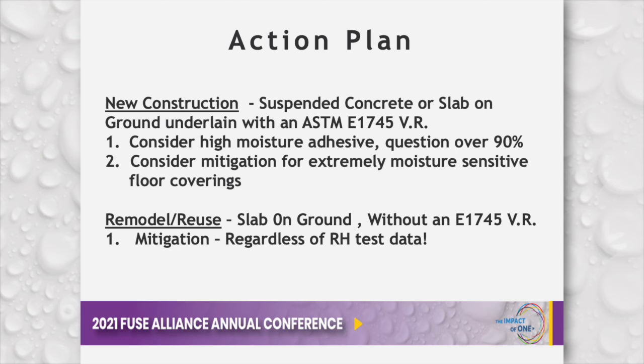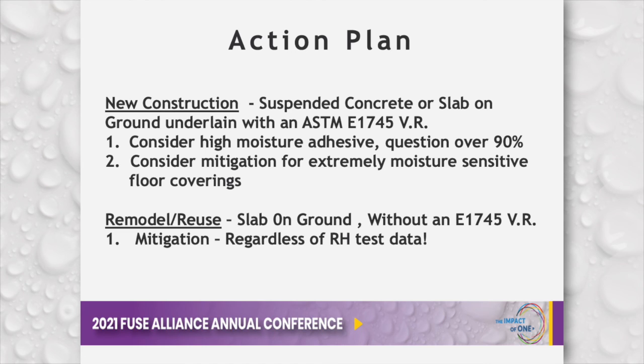So I would always consider mitigation for extremely moisture sensitive floor coverings. And frankly, unless I know how that building is going to be HVAC controlled, I would consider it for anything over 90%. But I understand if you have to use a high moisture adhesive without that ability to control temperature and humidity, understanding if you cross dew point, you may have a floor failure. When we look at remodel or reuse slab on ground without that E1745 vapor retarder, I am going to say mitigation is absolutely critical regardless of the RH test data and for all the reasons that I hope we've outlined today.